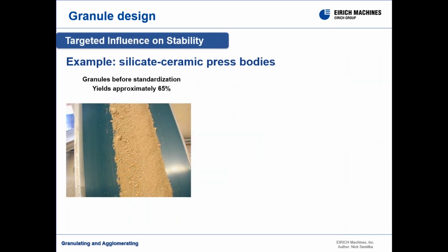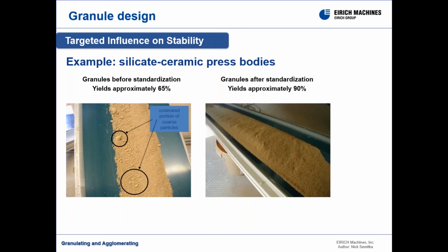Here is an example before and after stabilizing a granulated material in the Eirich optimizer. Product material coming out of the mixer, we were seeing yields of 65%. Processing the materials through the optimizer, we increased the yields up to 90%. Now you see a nice product without any large agglomerates and uniform properties.